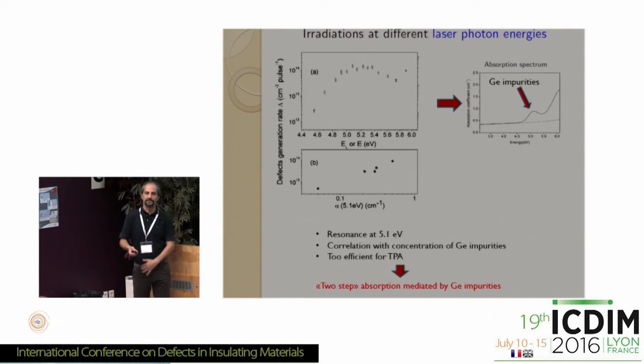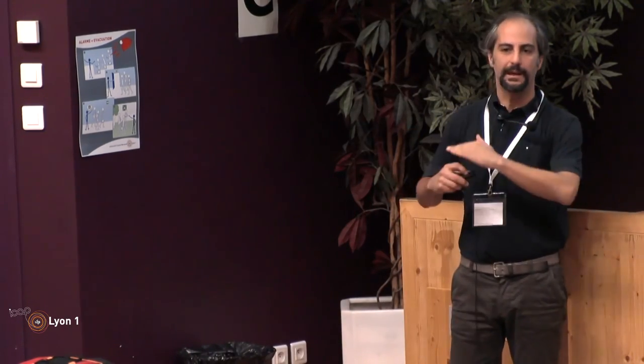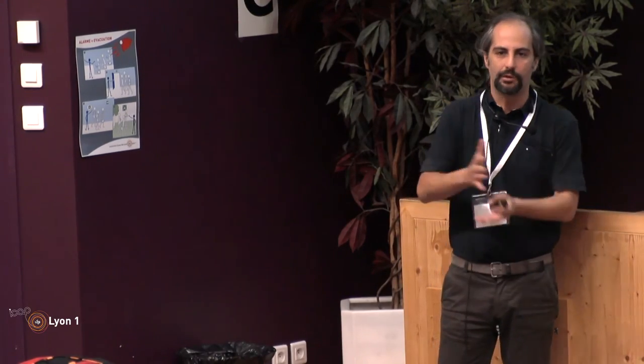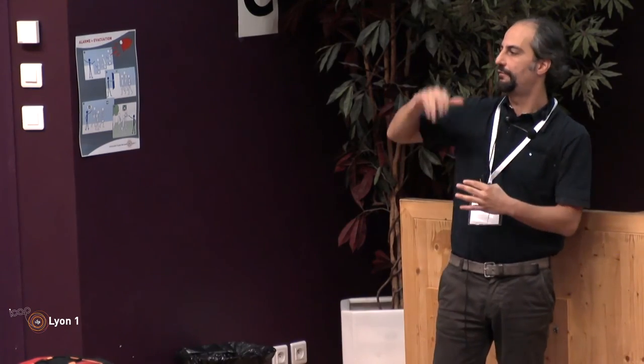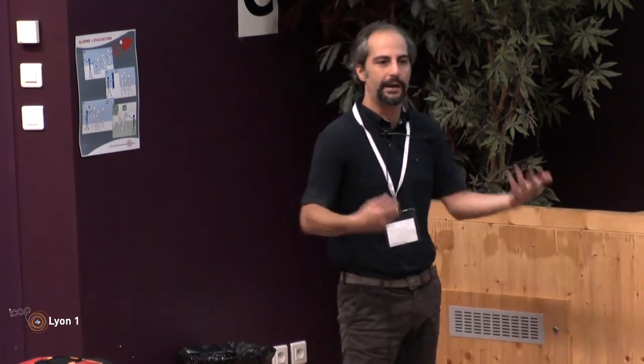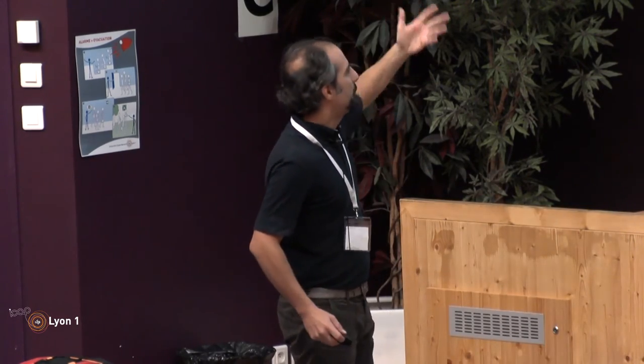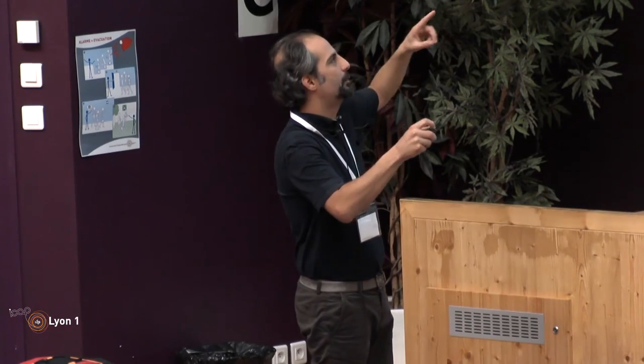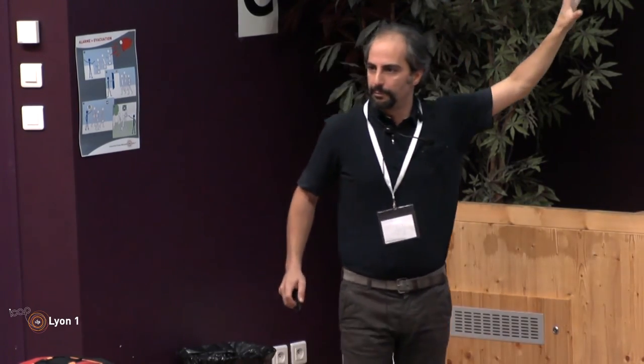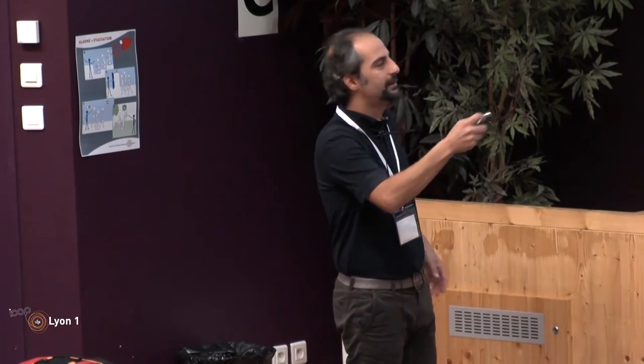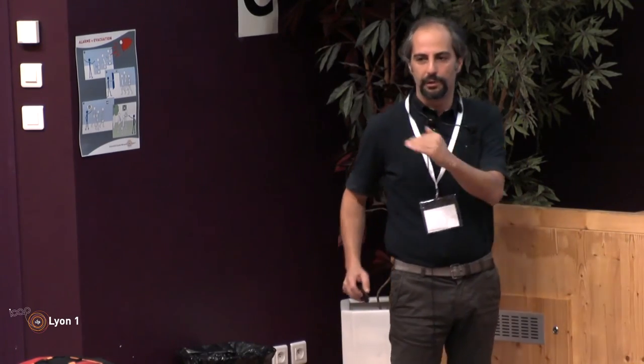So overall, this proved that germanium impurities present in the sample provide a way to enhance the generation rate of point defects, in the sense that they introduce a mid-gap state around 5.1 eV, and then when you use a laser around 5 eV, you can use this state to jump much more efficiently to the conduction band, so to produce electron-hole pairs with a very large efficiency. And this ultimately results in the generation of a lot of defects. So the message here is that even a very small concentration, because here we are talking about parts per million of germanium impurities, if they provide a level where you are not supposed to have a level, can lead to a material which is very easy to damage by laser radiation.